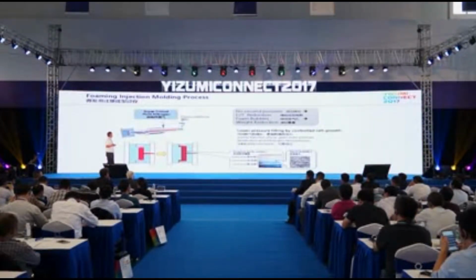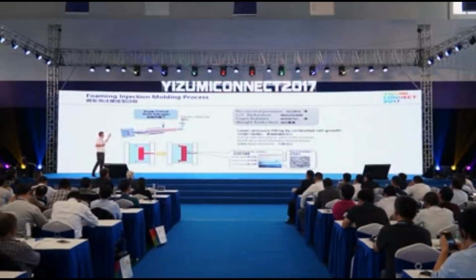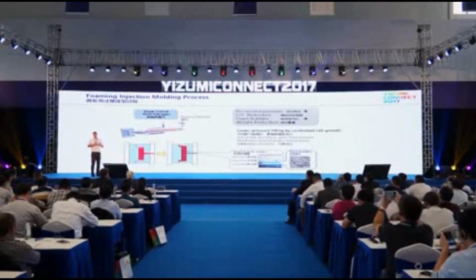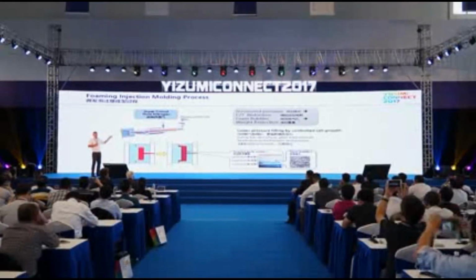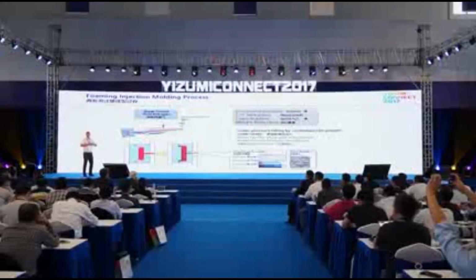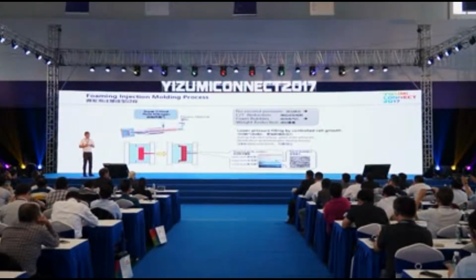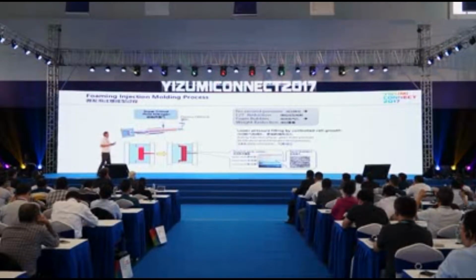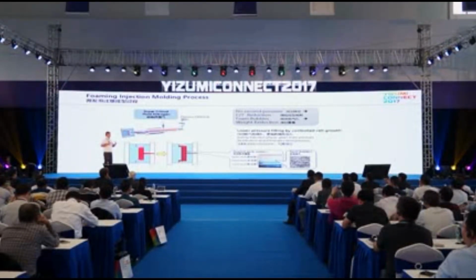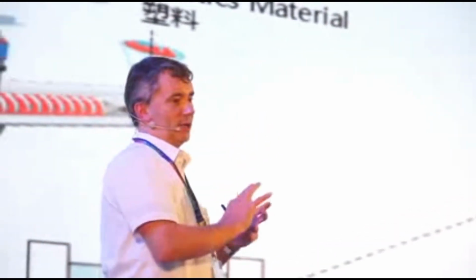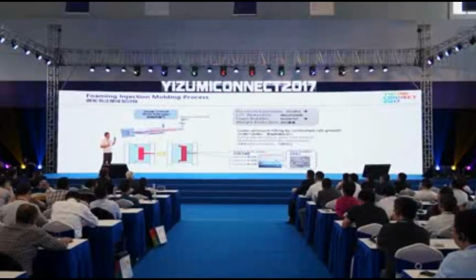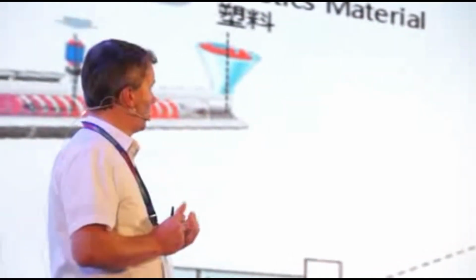So, foaming technology. I'm sure most of you are aware of the technology, but it's basically a supercritical fluid, either nitrogen or CO2, is injected into a modified screw. When you inject the plastic into the mold, you have a low pressure, and this starts the foaming process. Okay? As you can see here. So one of the advantages of the foaming process is you don't have what we call the second pressure. Normally when you inject plastic, you inject 99, maybe 100% full, and then we need to put high pressure to stop the shrinkage effect of plastic. And a lot of what we do in the industry is based around this problem. So it takes away that issue. So we have cycle time reduction, we have a density reduction from the bubbles, and we have a weight reduction.